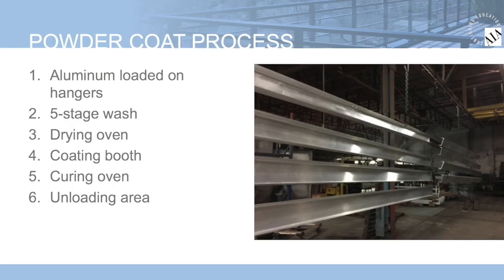The aluminum must be sent through the drying oven where the moisture from the pre-treatment stage is removed. Parts normally spend 2 to 4 minutes in the oven around 380 to 420 degrees. The conveyor will move the aluminum through the powder coating booth at a steady rate so that the application guns cover the aluminum properly in order to meet the AAMA 2604 or 2605 standards. The powder should be cured for 8 to 10 minutes at around 330 to 460 degrees depending on the color and the part's density. When the aluminum is cooled, it is then unloaded and packed for shipment and delivery to the customer.